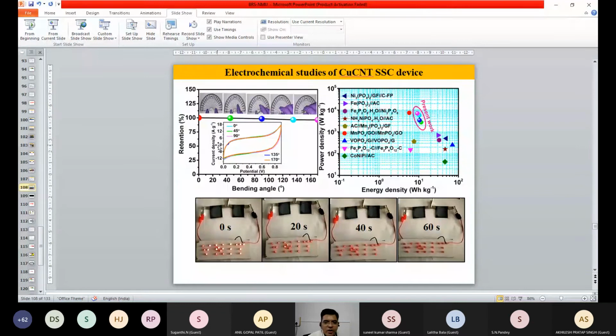So again, we have done this with respect to the bending angle, and we have seen that the retention is close to 100%, up to a 170-degree bending angle. Whatever device we have formed is very, very stable with respect to the bending angle. It is close to 100%. So it is more than 95%, we can say. Stability is there, although we are bending up to 170 degrees.